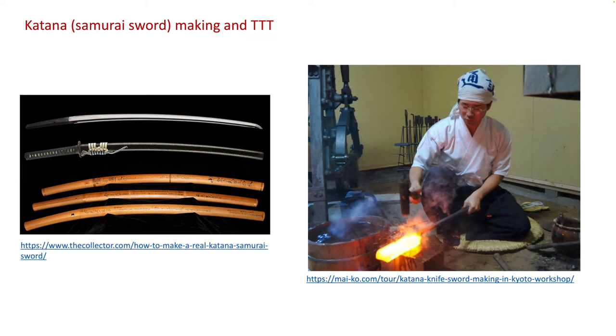In the final slide, I want to quickly discuss the steel making, which is an ancient art. The blacksmith usually hot works the steel and quench it in cold water. And one thing I learned from a documentary is quite interesting. When making the Japanese samurai swords, katana, the blacksmith will only dip the blade at the very edge of the sword in water to locally fast cool the blade. This encourages the blade of the sword to turn into martensite, whereas the back remains either bainite or ferrite.